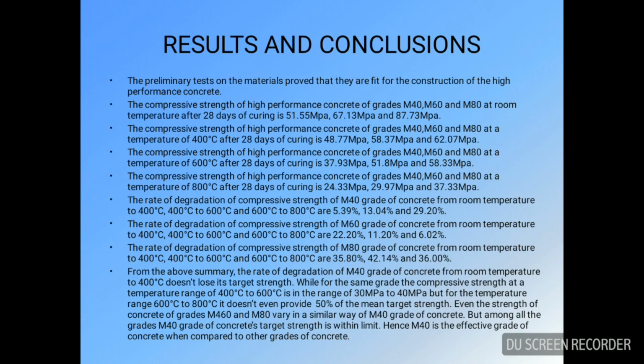At last, the rate of degradation of compressive strength of M80 grade of concrete from room temperature to 400 degrees Celsius came around to be 35.80%. For 400 to 600 degrees Celsius, it came around to be 42.14%. For 600 to 800 degrees Celsius, it came around to be 36%. As you can see, for M80 grade of concrete the rate of degradation has been on the highest side, like 30%, 35%, 40%, and again 35%. Among these three grades of concrete, only M40 had a lesser range of rate of degradation, like 5%, 13%, and 29%.